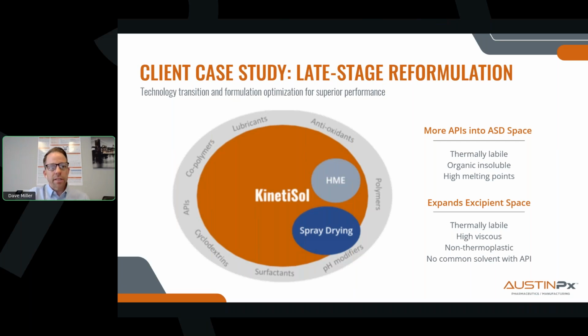So we can process these high melt point compounds almost independently of their melting temperature, several, up to 100 degrees below the melting temperature, in fact. And with KinetiSol, you can work with polymers that are non-thermoplastic, highly viscous, or insoluble in organic solvents. And to these, you can add virtually any other adjuvant material like lipids, surfactants, stabilizers, what have you,